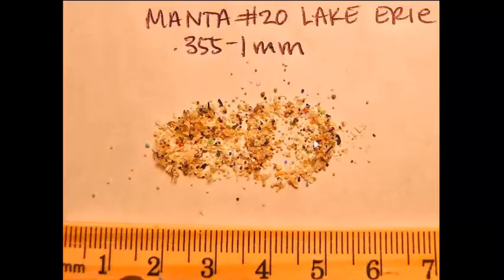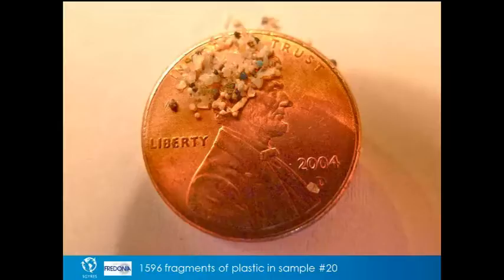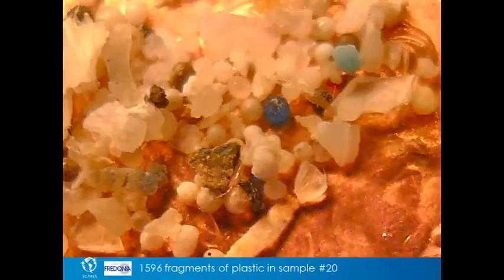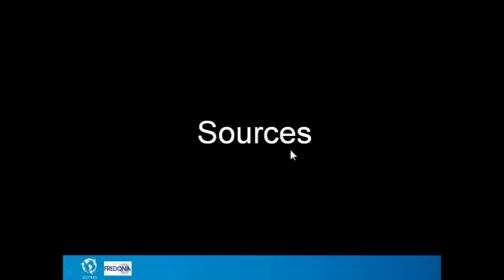So this gives you an idea of these plastics, what we're finding in the smallest size classification. You'll notice that a lot of them are these perfectly spherical, highly colored little balls of plastic, quite beautiful in their own way. And so, what is the source of these? The fact that they're so perfectly spherically round means that this isn't something that was bigger and broke down, but more likely something that was released into the water as a microplastic itself. So just showing you a few different images of these, and this really makes it easy to see how highly colored many of the particles are and how perfectly spherical. So, like I said, we're really thinking about, well, what are the sources of these?